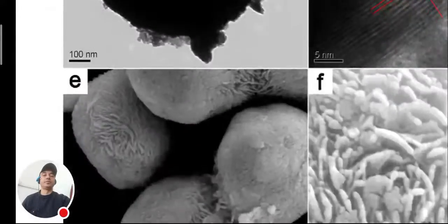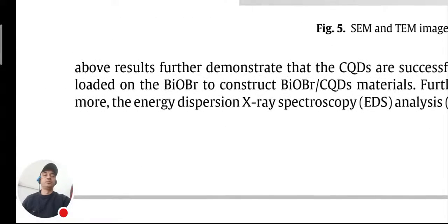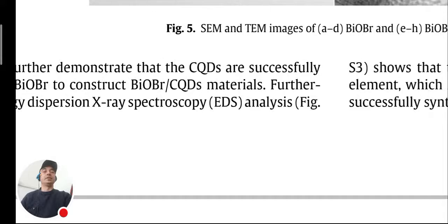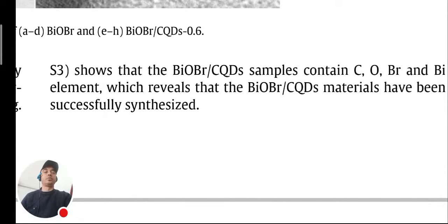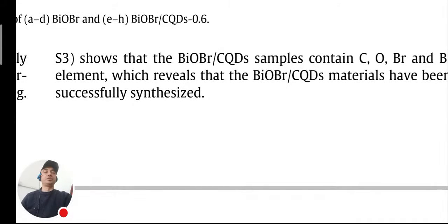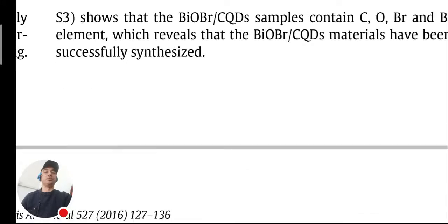These are the images we will see at the end, all figures. The above results further demonstrate that the carbon quantum dots are successfully loaded on the BiOBr to construct the BiOBr carbon quantum dot material. Furthermore, the energy dispersive X-ray spectroscopy (EDS) analysis figure shows that the BiOBr carbon quantum dot sample contains carbon, oxygen, Br and Bi elements, which reveals that the BiOBr carbon quantum dot material has been successfully synthesized.